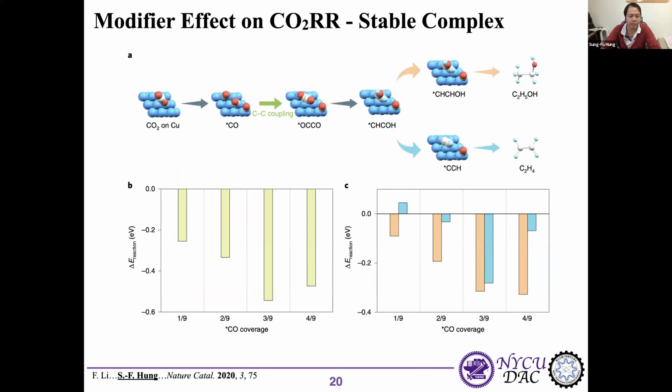Okay, so we study another interesting case. Through the calculation of the reaction energies comparing two different paths, here the first one is the upper one, and the lower one is the other. We found that the reaction energy was lowered when the additional carbon monoxide intermediate was introduced. The energy will decrease further with another carbon monoxide intermediate introduced in the system. So we concluded the adsorbate to adsorbate interaction becomes more remarkable with the increase of the surface coverage.